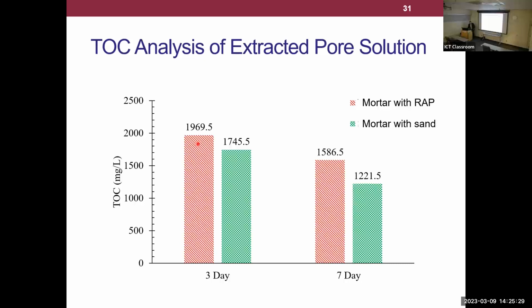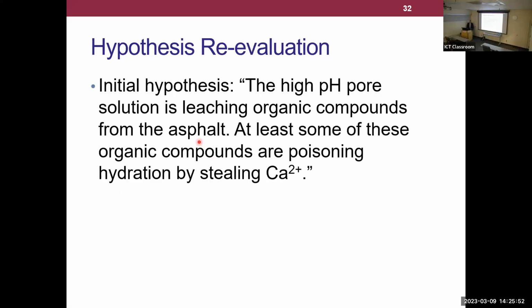But regardless, if this is our control, because of the fluoropolymer in the die, we still see a larger peak here for mortar with RAP. So we definitely know that we are getting leachate in our concrete. First we proved it just by soaking in an NaOH solution. Here, this is actually in pore solution. And yes, we definitely have organic compounds. So let's reevaluate. We're thinking that the high pH pore solution of the concrete is leaching those organic compounds, and those organic compounds are somehow affecting cement hydration. We haven't quite proven this last part. We thought it's just stealing calcium from solution. We don't know if that's true yet. That's future work. But at least what we've shown so far is that we definitely have organic compounds in the leachate, in the pore solution, and we definitely are seeing some effect on cement hydration.